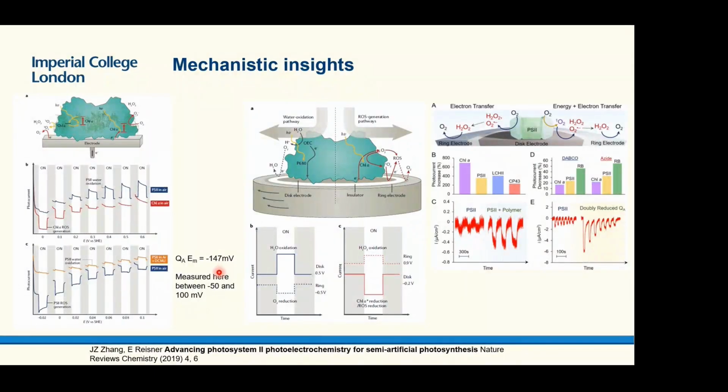It's possible that it's due to the interaction of the protein with the surface, but it's also possible that there are some limitations associated with the conductivity of the ITO that could change when it's in a mesoporous structure, because you get a non-uniform distribution of the dopant, and then in this case the conductivity decreases.